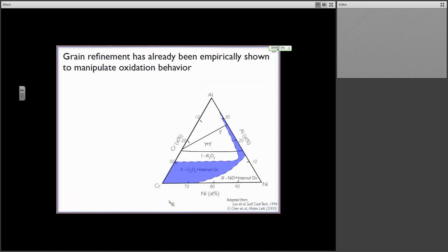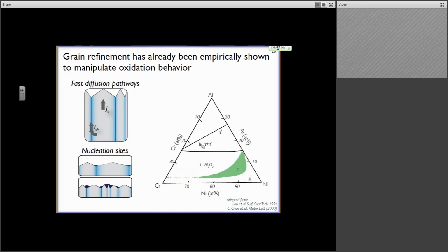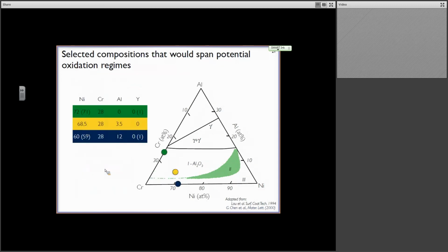In fact, we have shown in the literature, empirically at least, that if I take the same oxide map that I showed you before, that chemistry influences the type of oxide we get, and I change the grain size by an order of magnitude, I shift that whole favorable aluminum oxide region down to much lower aluminum concentrations. So even though I don't have as much aluminum in my system, because I have these fast diffusion pathways along my grain boundaries, and because I now have a plethora of nucleation sites, I can grow and develop a desirable oxide scale much faster, and it becomes protective even though I haven't changed the chemistry. Okay, so we've seen this empirically. Now we need to understand a little bit better actually why this is happening.